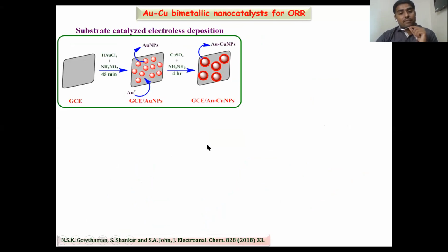We also fabricated the gold copper bimetallic nanoparticles without synthesis. In the earlier case, we synthesized the gold platinum bimetallic nanoparticles in the solution form, and then we fabricated them on the electrode surface. In this case, we directly fabricated the gold copper bimetallic nanoparticles without synthesizing in the solution form. So here, initially the gold nanoparticles were fabricated on the substrate by electroless deposition with the help of hydrazine as a weak reducing agent, and then the gold nanoparticles fabricated substrate is immersed in the solution containing copper sulfate and hydrazine, and the copper nanoparticles were fabricated on the surface of gold nanoparticles.